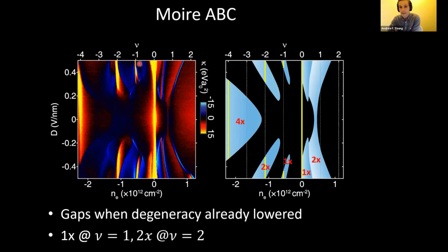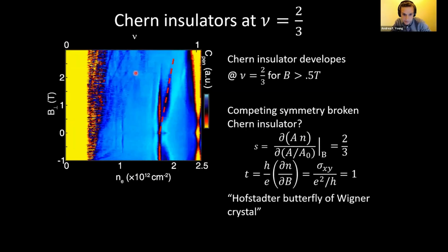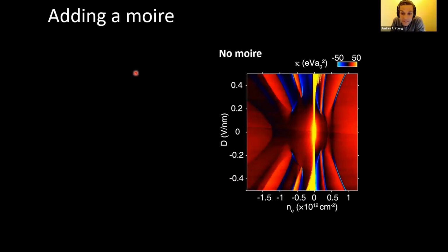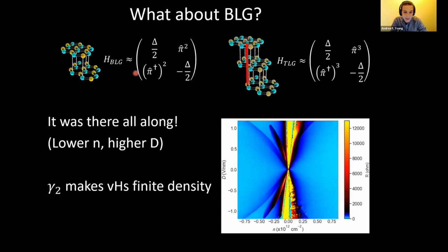This is as low as you can make that density for graphene hBN because hBN and graphene have a lattice mismatch. So there's just a maximum Moiré wavelength that you can get. In Bernal bilayer, all of this happens at considerably lower density. So I think, well, okay, let me take it back. It is possible. It's just we need to go to some very large density. I think I need to look at the numbers, but nu equals -1 is going to be something like 0.75 or 0.5, times 10 to the 12.